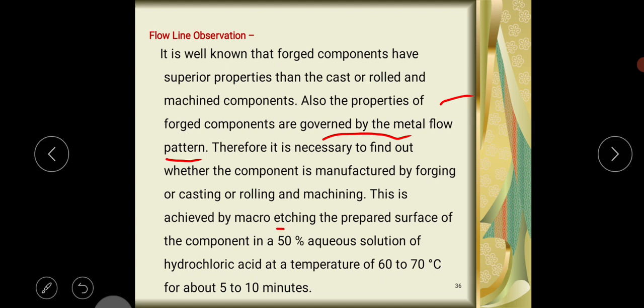This is achieved by macro etching the prepared surface of the component in a 50% aqueous solution of hydrochloric acid at a temperature of 60 to 70 degrees Celsius for about 5 to 10 minutes.